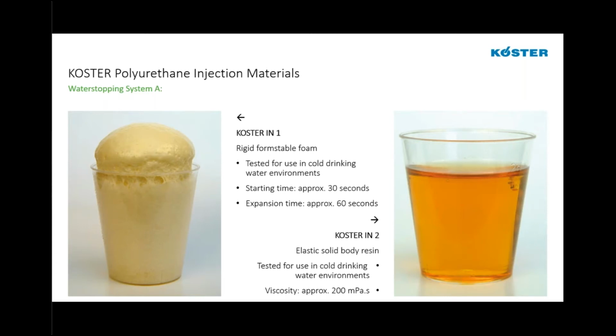Both these products are tested and certified for use in drinking water environments, but the IN 1 is a very expansive, rigid polyurethane foam that starts reacting about 30 seconds after it encounters water, expands for about a minute or more, depending on the agitation. Like we said, these foams don't have a very, very long lifespan in terms of breaking down either from movement or from just normal conditions.